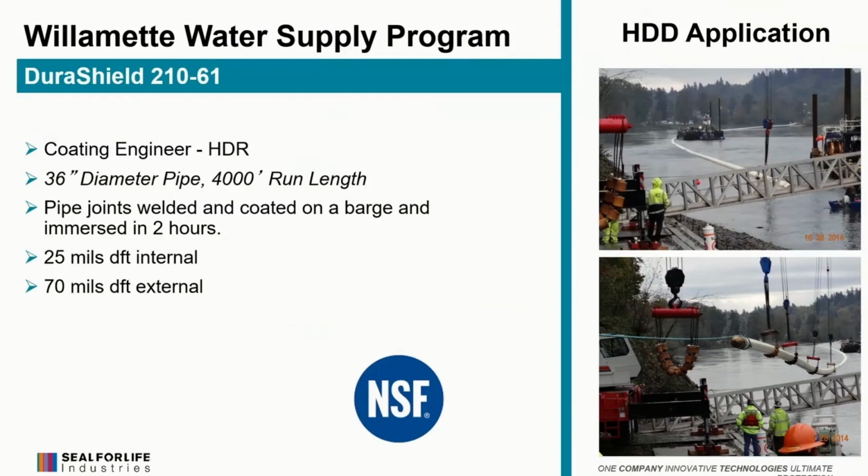So compare that to epoxies. Most epoxies, not all of them, there's some that are flexible, have a little bit better impact, but standard epoxies that you're going to use in this situation, 8, 10 pounds direct impact, if that. Their flexibilities are usually 3 to 5%, where once again, 310 is 40%, 210 is about 15%, and 110, being the hardest, is still at about 10%. So these are the things that they take into consideration.